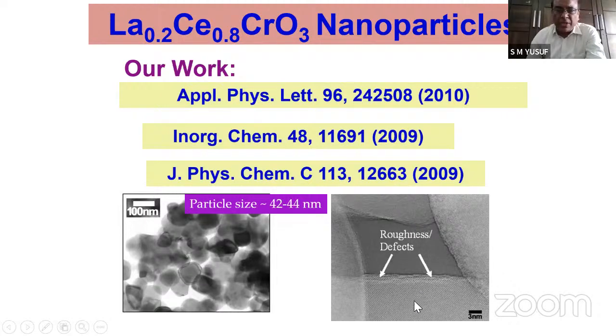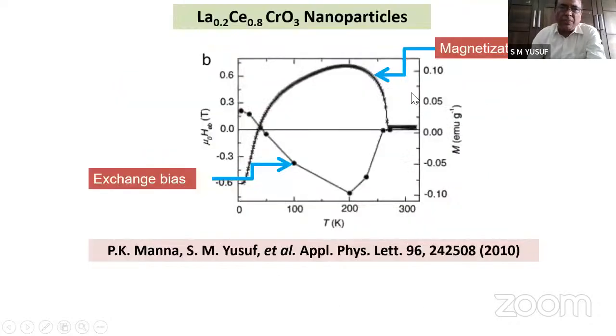So that creates the interface, which also shows this kind of magnetization reversal, the top one. But interestingly, along with the magnetization reversal, you see another one, what is called exchange bias. Exchange bias also shows the reversal property, and there is a one-to-one, a mirror image of that. As you all know, exchange bias is very important in magnetic memory devices. I will be touching upon, at the end of my talk, the relevance of this magnetization polarity reversal and exchange bias reversal.